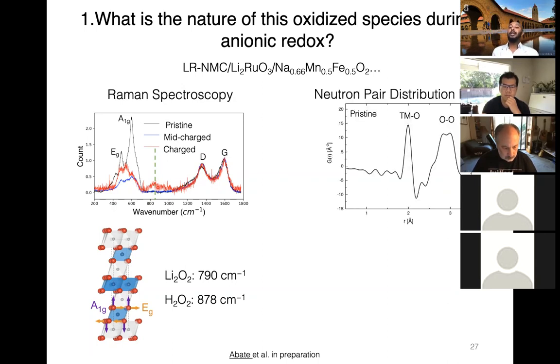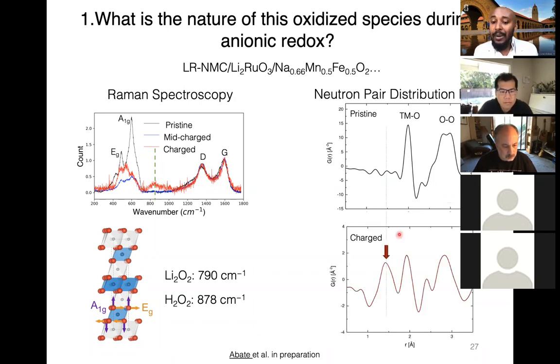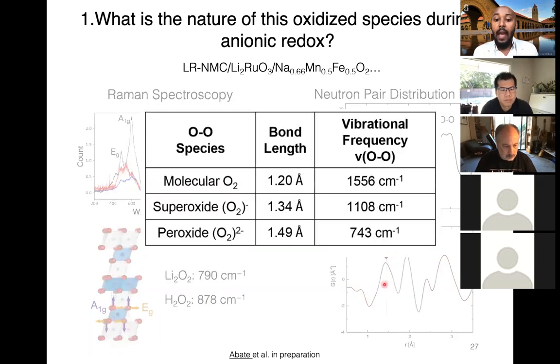We also use a technique called neutron pair distribution function, in short neutron PDF, as a method to measure the scattering lengths or the bond lengths between two neighboring atoms. Using neutron PDF to look at battery materials, we found out that the metal-oxygen bond is close to 2 angstroms, and the oxygen-oxygen separation distance in the pristine material is close to 3 angstroms. But the most important change, again, upon charging is, in addition to the pre-existing peaks, we have a new peak close to 1.5 angstrom from the neutron PDF measurement after anionic redox. And this bond length is very close to the peroxide bond length.